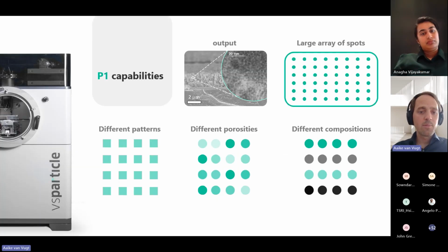So one of the benefits is that you can make these patterns. You can make these arrays of samples in a single fully automated script. And they can all be the same composition, or they can be different compositions and also different porosities. So the nice thing is that you can program the printer with scripts to change the printing time, to change the printing conditions, to change the porosity, but you can also change the output of the 2 sources to change the elemental composition from spot to spot. And this really opens up new capabilities, both in nanoparticle-based nanoporous thin films, but also in the field of high-throughput self-driving labs.